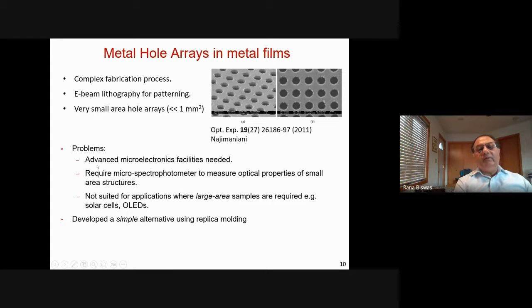So obviously, you need very advanced microelectronics facilities. And then to make these optical measurements, you require a micro spectrophotometer to measure optical properties of very small area structures. And this approach is then not suited for applications where you need very large area samples, like solar cells, and organic light emitting diodes, and even most optoelectronics. So what this motivated us is to develop a simple alternative to this fabrication process. And here we use replica molding.